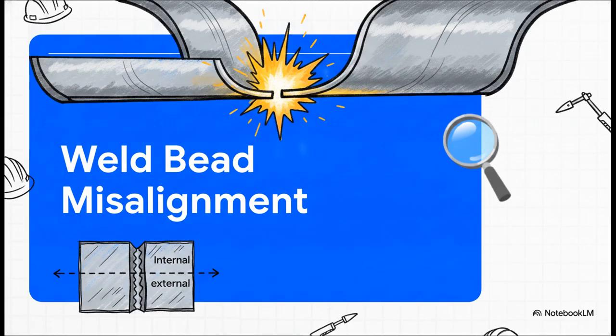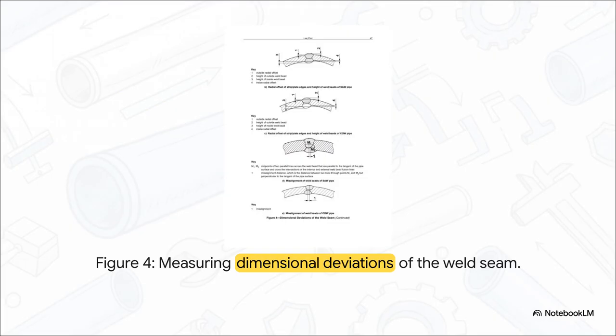They define weld bead misalignment precisely as the distance between two parallel lines drawn across the internal and external fusion lines. So to actually measure this in the field, inspectors have to find the midpoints of both the inner and outer weld beads, draw a line perpendicular to the pipe's tangent, and calculate the exact radial offset distance. This kind of complex geometric measurement is what ensures that structural forces flow evenly across the seam, rather than creating this deadly localized tearing force.